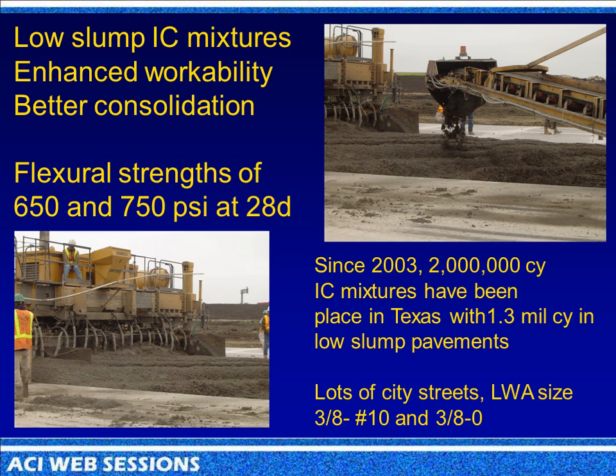Now, the workability is also great. I mean, they love it with these internal curing mixes. They perform the same way right behind the pavers. But since 2003, in Texas, they've done over 2 million cubic yards of internal curing mixes. And these are low slump. About 1.3 million have been low slump on pavements. And most of these are on city streets. And they're using either the 3/8 by 10, which I showed you that example, or they're using a 3/8 by 0. And probably the bulk of the work outside of Texas is with the finer gradation, the 3/8 by 0.